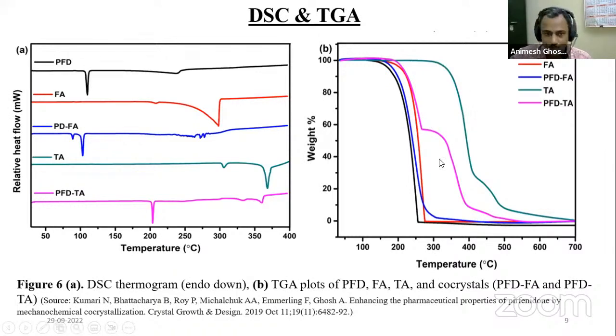This is nothing but the corresponding thermogravimetric analysis. It gives the information about at which temperature range the sample starts to degrade and when its degradation completes. From the thermogravimetric analysis, we can confirm that melting is not accompanied by degradation, because degradation starts after melting. If we see, approximately after 150 or 200 degrees Celsius, it starts to degrade. That means this is the phase transition. This is not the decomposition. In many cases, decomposition might give an endotherm peak, although generally decomposition will give you an exothermic peak. But to confirm that this peak is exclusively for the phase transition, that means solid to liquid, we need to do the thermogravimetric analysis, from which we can say that yes, it is a phase transition, not decomposition or degradation.